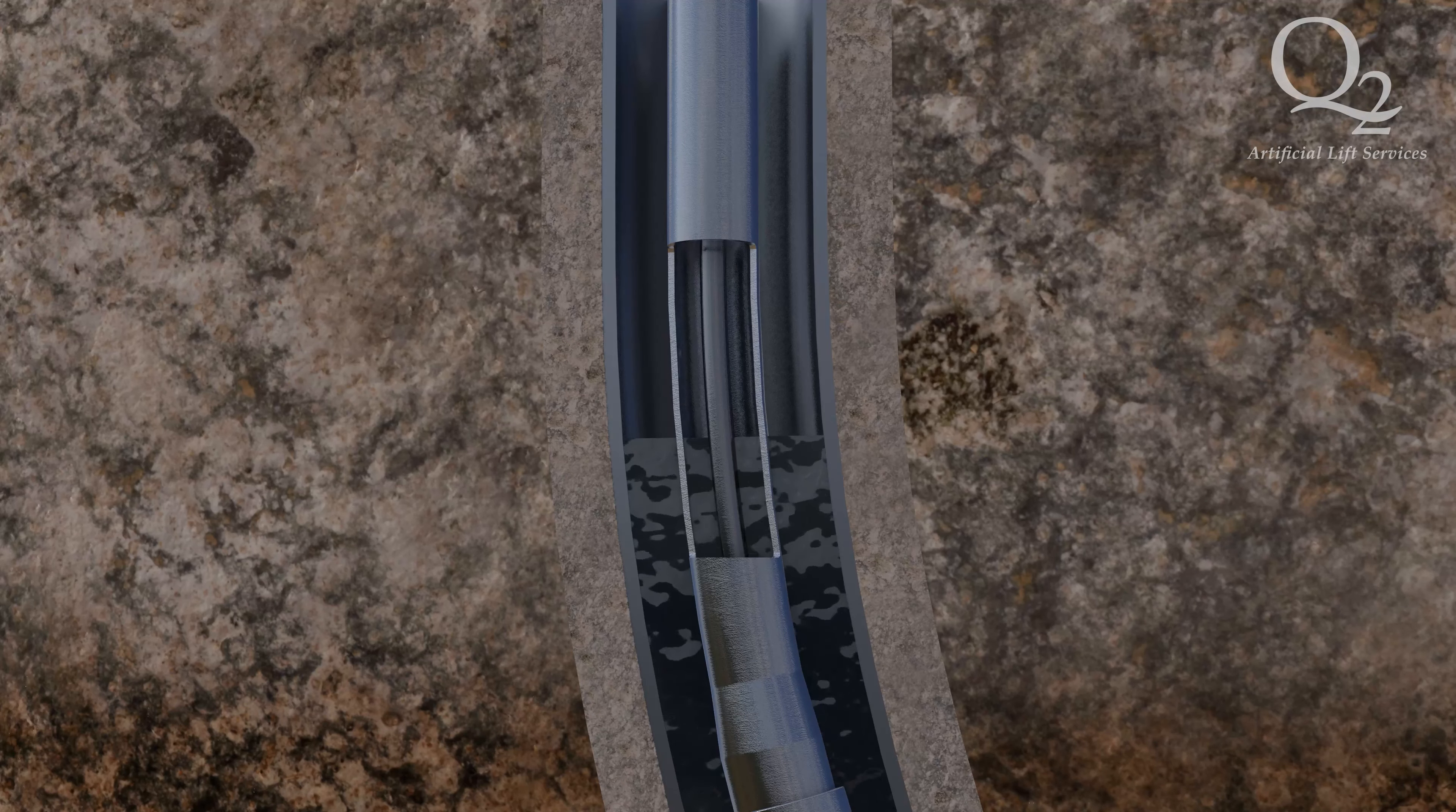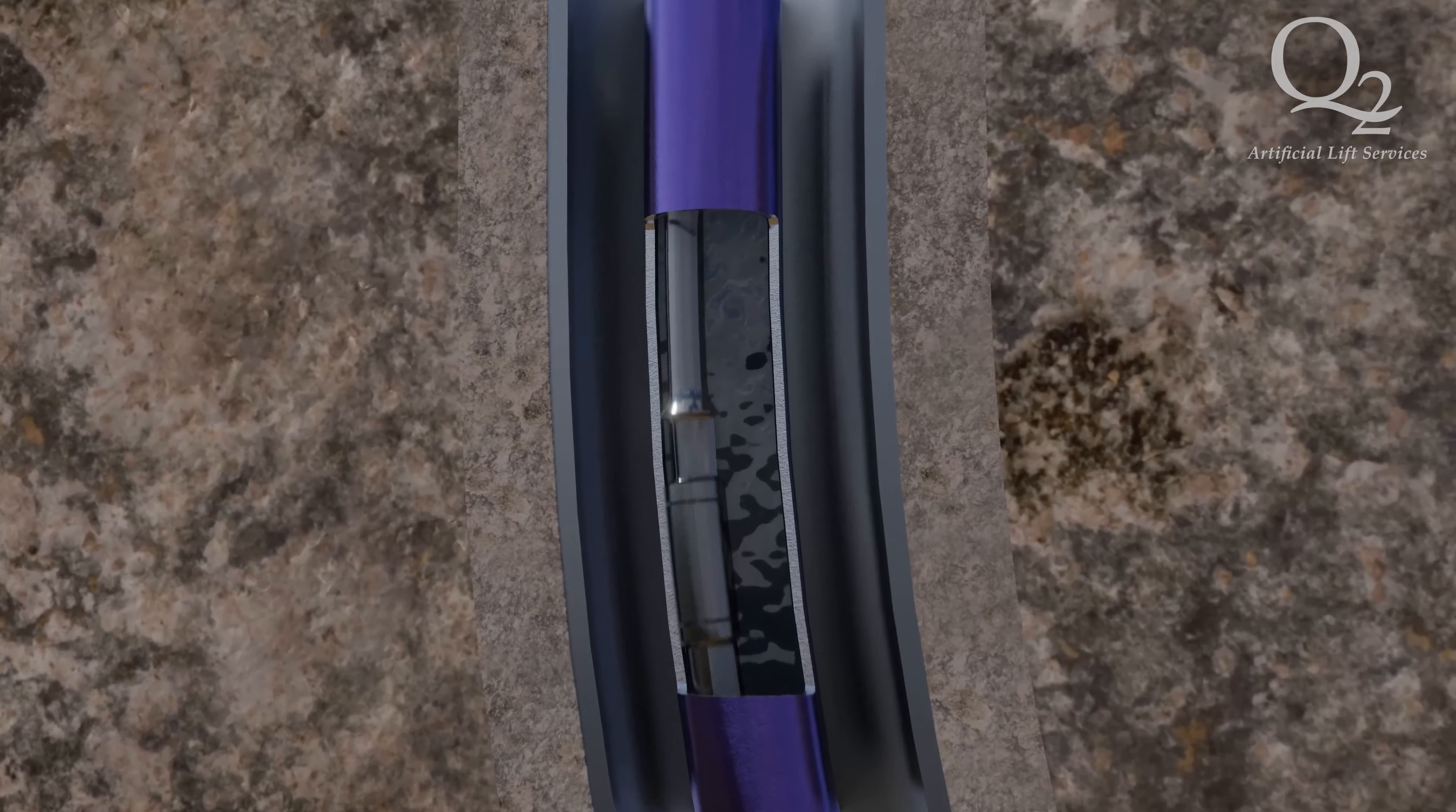This portion of video identifies the colored area representing Q2's CPT tubing. The combination of the electroplating and the ceramic particles helps give the CPT a smooth and extremely hard surface finish, which helps prevent both premature wear and the buildup of scale and gypsum.